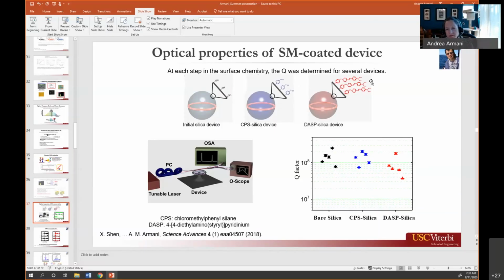And then you develop whatever your third molecule is, your third functional group, and you develop it such that only the left side of the molecule will bind to the chlorine and the right side won't. And so then it's a self-quenching reaction. So you only get a monolayer and it only bonds in one direction. If you think of it like Legos or bricks, you design it such that it only wants to stack in one direction. So it's a lot of chemistry. If you talk to a surface chemist, this is really easy. It's a matter of optimizing your surface chemistry such that your surface chemistry process doesn't damage your device. That's the hardest part.